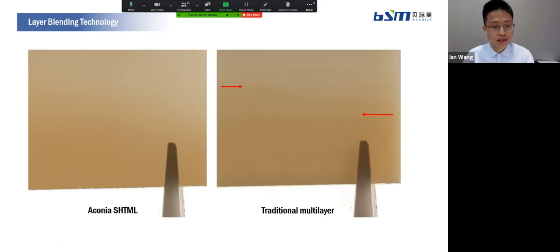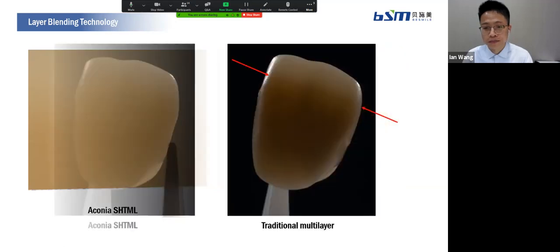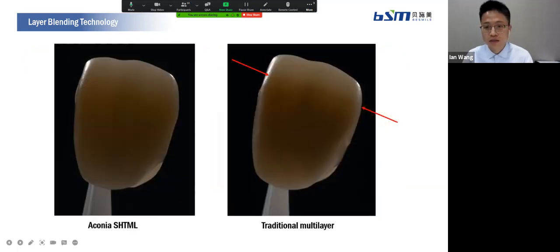So, we made some samples from Aconia SHTML and the traditional multi-layer. And we can see for the traditional multi-layer, there will be a boundary between the different layers. And on the restorations, the boundary will be more obvious. But for our Aconia SHTML, because of the unique layer blending technology, the gradient is so natural and the restoration is very lifelike.